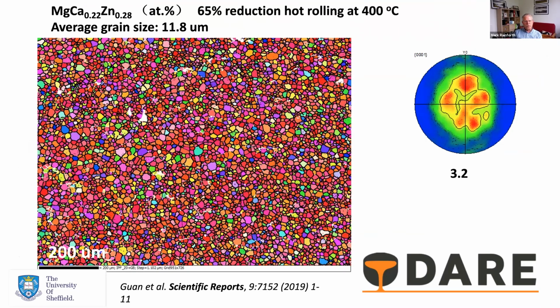So to cut a long story short, this is quite a lean alloy, so magnesium with a small amount of calcium, small amount of zinc in. We now get a very uniform grain size within the material. And as you can see on the right-hand side, the texture is nicely distributed, and it's a very weak texture. So we know that this alloy is very formable, and we know it also has adequate corrosion resistance, which is really going to be important, although protection is well advanced for these alloys. So manufacturers such as Volkswagen have been looking at these magnesium alloys as possible commercially viable routes.